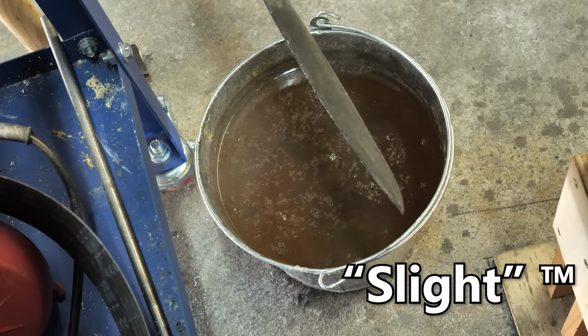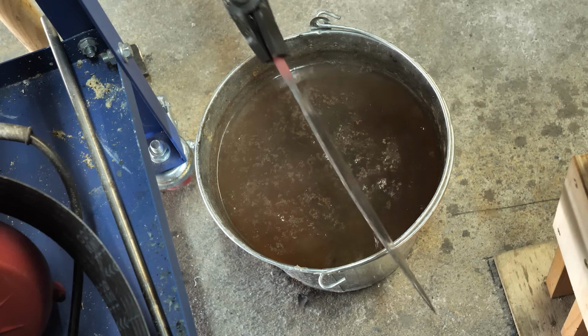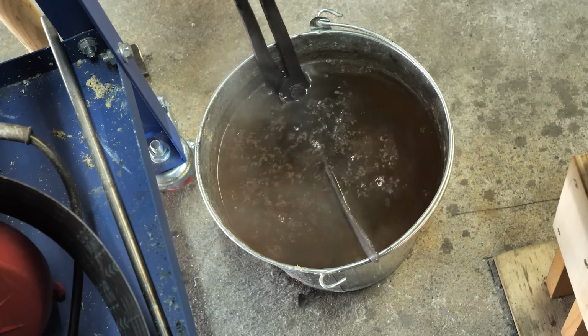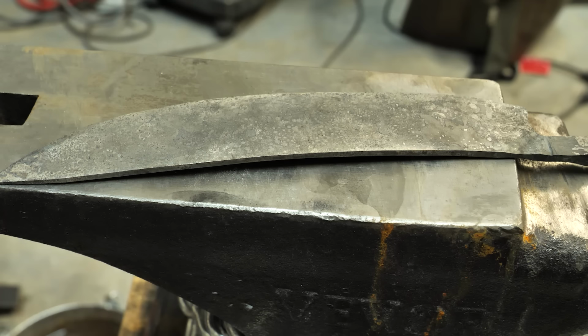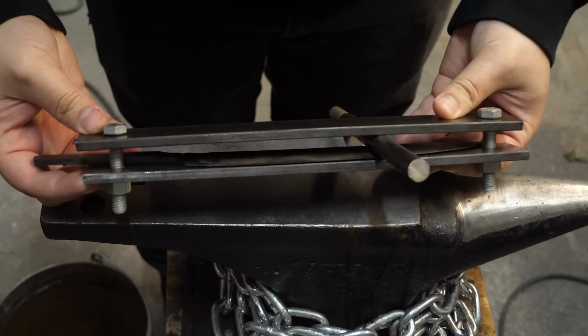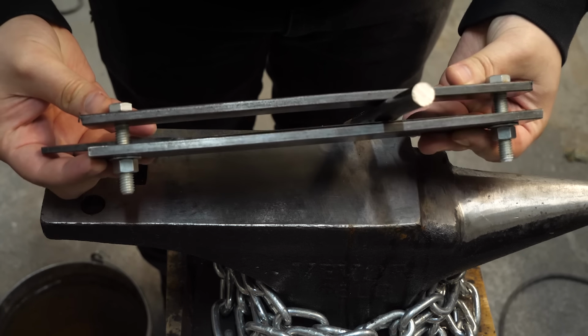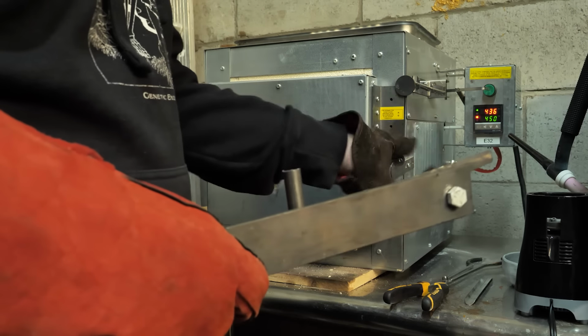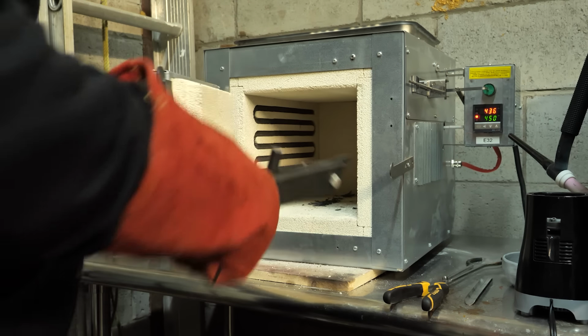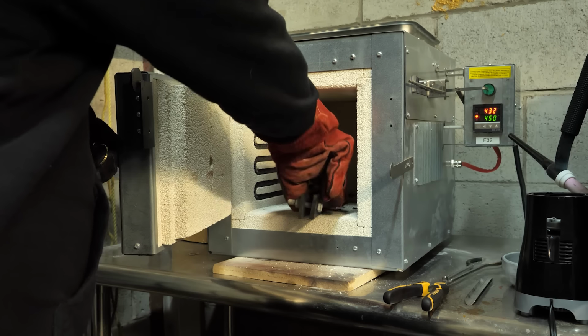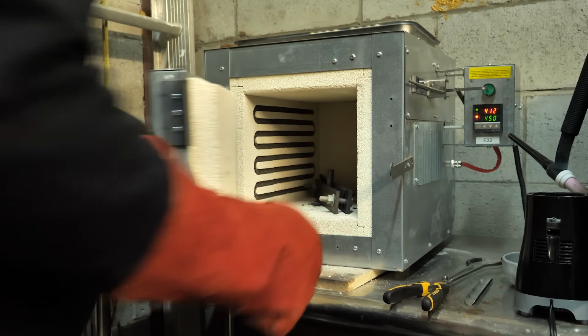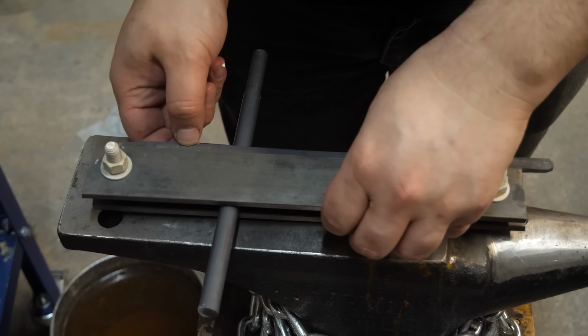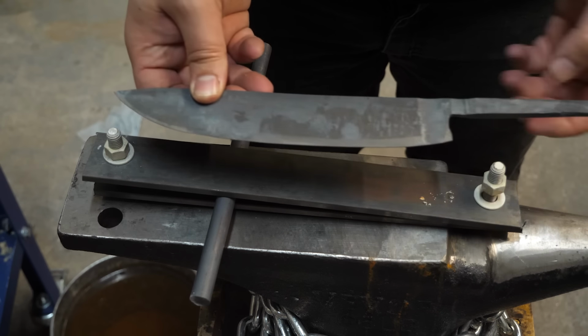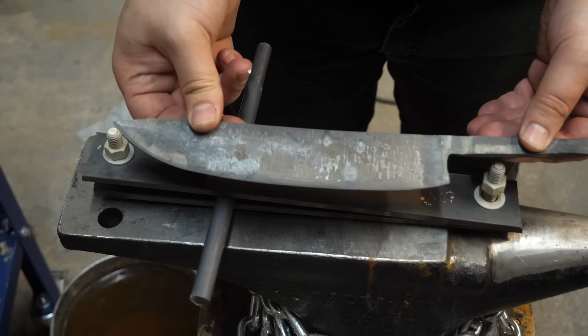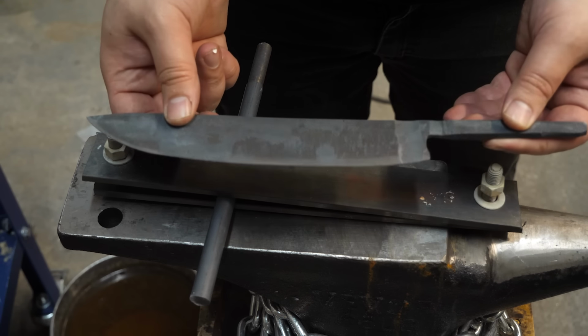The knife picked up a slight bend to it after the quench, and in the freshly quenched state, it's actually too hard and risks being brittle. So what we're going to do is something called a shim temper. This means cooking the knife while it's clamped in a jig that is gently bending it straight. By cooking at about 450 degrees Celsius for an hour or two, the metal will soften a little bit, but become much more tough in exchange. The result is a balance between strength and hardness, so the final tool is ready for plenty of use and abuse. Or, at least, it should be.